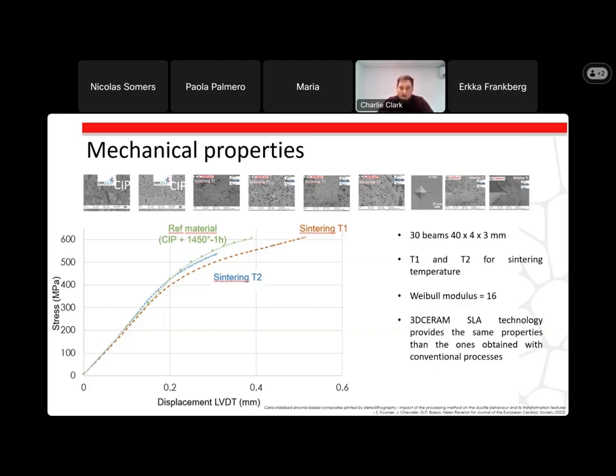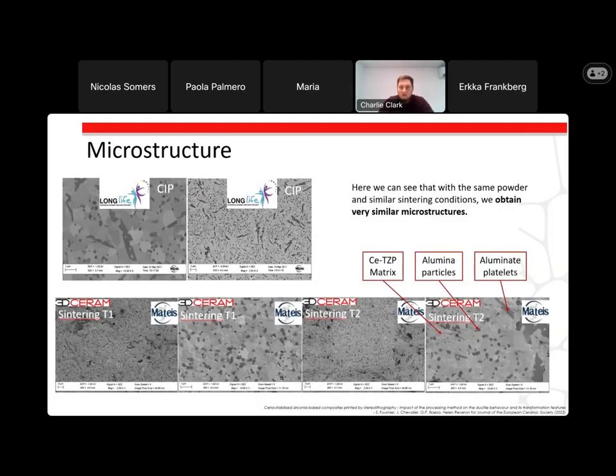And what we can see here is that the properties obtained by the 3D printed parts and the conventional method parts differ ever so slightly, but insignificantly, when we're looking at sintering with the second temperature. What we can also see, looking under the microscope, are very similar microstructures. So you can see in the different parts that were obtained, with the 2 different sintering temperatures but also the parts obtained by conventional methods, that we could still find the matrix, and we could still define where the particles were and where the platelets were.